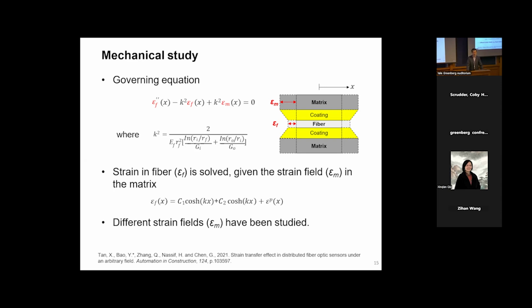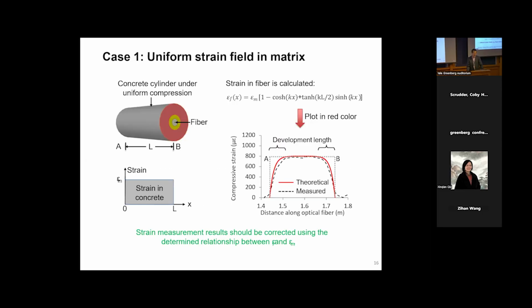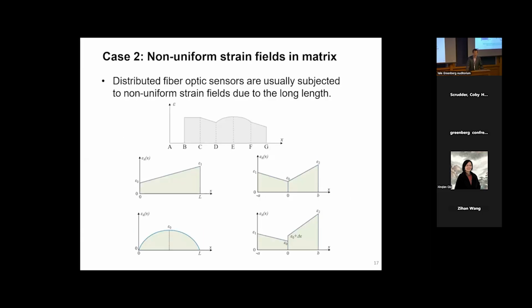But fortunately, we were able to do the mechanical analysis and develop this governing equation. Then by solving this governing equation, we can determine their relations. This is very simple if you have a point sensor, because the sensor length is very short. You can consider the strain field as a uniform strain field. And there will be a development length, which is probably very familiar for our structural engineers, because this is a general phenomenon for reinforced concrete or pre-stressed concrete.